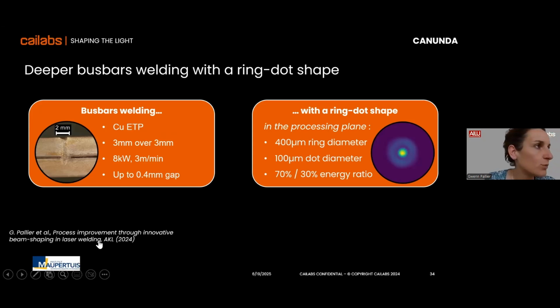One last one, which, to be honest, was a little bit surprising for us, is when you're welding copper, what is globally difficult is to go very fast or to go very slow, because in both cases, the melt pool is not that stable. And if you want to weld deep, and you have a fixed power, you don't want to use more than 8 kilowatt, for example, actually you have to go super slow, 3 meters per minute.